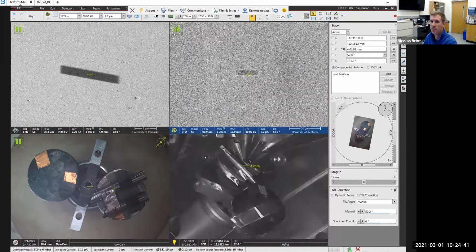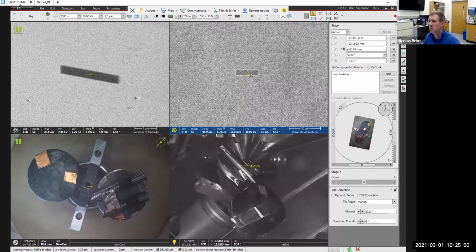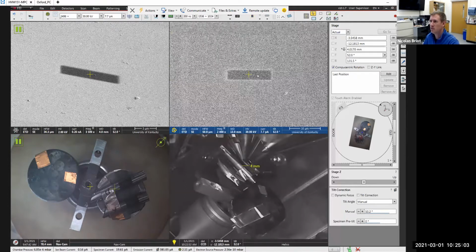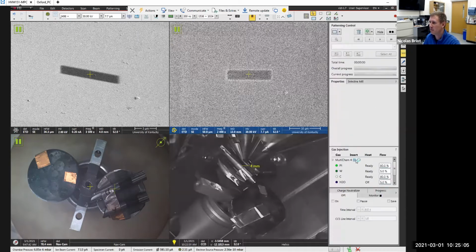And see how I'm pausing pretty rapidly? It's because I'm generating an image based on the FIB scanning. But as it is scanning, it is milling the material away. So I don't want to just scan and erode my surface forever, because eventually you get rid of the surface you're trying to analyze. So I just want to position things close to where I want them to be. I'm going to reinsert the tube and deposit a little bit more carbon just on top of the one we've done.